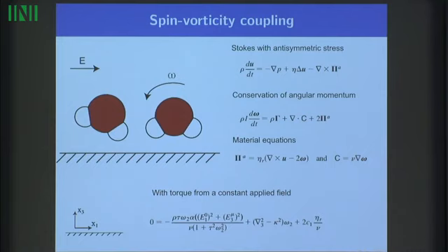So that's I think a nice calculation, because this mechanism has been suggested many times, and it's still actually being published occasionally that this works. If you do for example an MD simulation, you can easily produce some sort of a mobility out of nothing. So still occasionally papers come out that claim that this is possible. It's not. It's definitely impossible. You need some sort of a charge separation in order to produce a non-zero mobility. So that's the next thing that I'll be talking about.